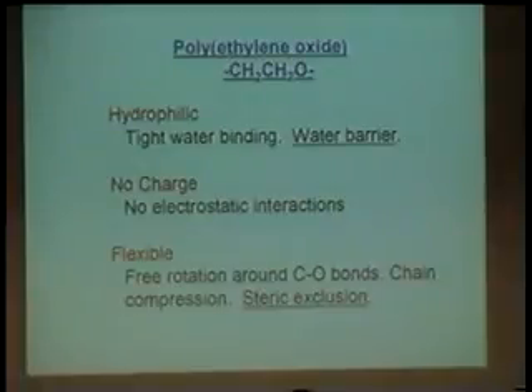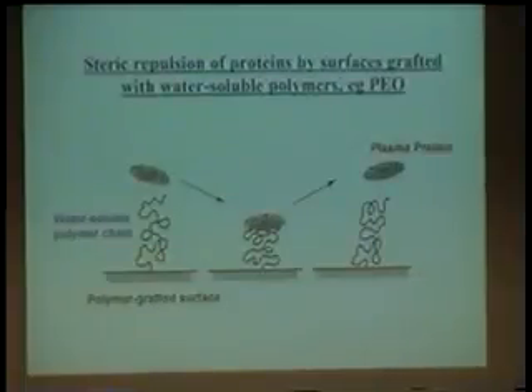This makes the polymer easily deformed, easily undergoing changes in conformation. So if it's attached onto a surface, it can be compressed very easily as a protein approaches. And this leads to the idea of steric exclusion, which is explained rather simplistically in this cartoon.